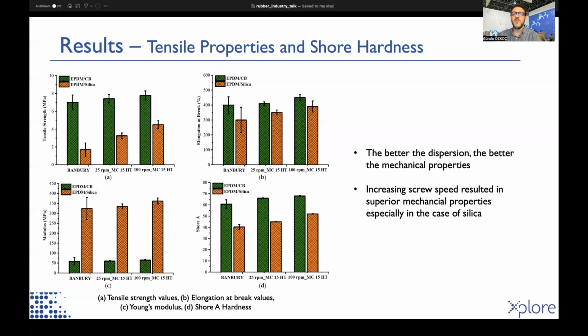The interfacial interaction between polymer matrix and fillers was a much more effective criterion for higher tensile strength and elongation at break values in particle reinforced polymer composites. The interfacial interaction between filler and matrix, the interaction between filler and other components such as accelerators and activators, and the level of dispersion of the fillers in the rubber matrix were significant parameters to obtain improvement in tensile strength of rubber-based composite materials. Therefore, higher elongation at break and tensile strength values of both EPDM carbon black and EPDM silica compounds were due to the finer dispersion of filler in EPDM, which were prepared in the microcompounder.